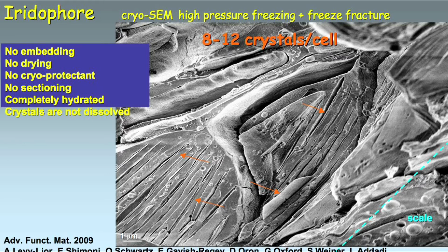Now, this was, again, something that was unknown until a very short time ago. And the reason is that what the scientists that studied this system had been able to do was to study them by transmission electron microscopy. And these are dried samples, and dried samples, of course, don't have the same parameters of spacings that we want to measure. How can we do that? We can do that by using cryo-scanning electron microscopy that looks at the system as is practically, with no embedding, no drying, no other extraneous solvents or protectants, and looks at the system completely hydrated.